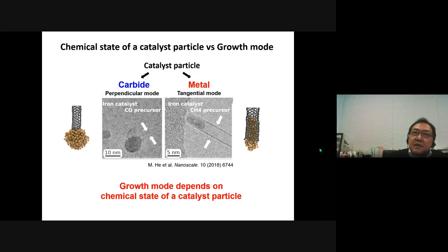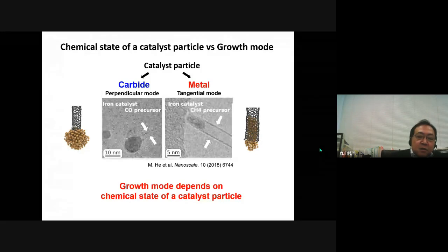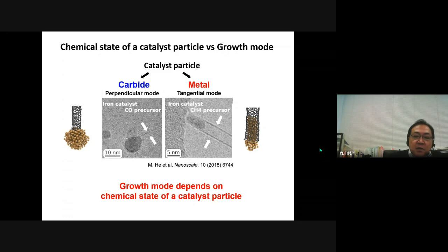So in particular, it has been pointed out that growth mode is determined by the chemical state of catalyst particles. A French group reported if catalysts are carbides, the tube diameter is smaller than the particle size. That is called perpendicular mode. On the other hand, if the catalyst particles are metallic, the tube diameter is almost the same as that of the particle size. That is a tangential mode. This means the chemical state of a catalyst particle determines the growth mode.